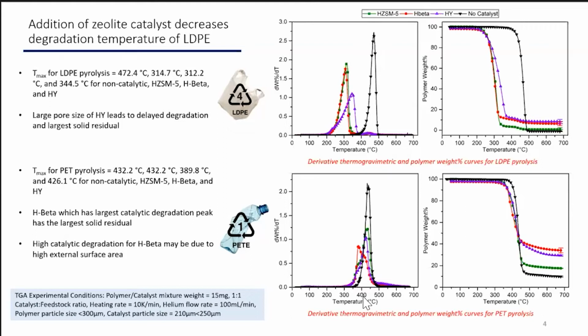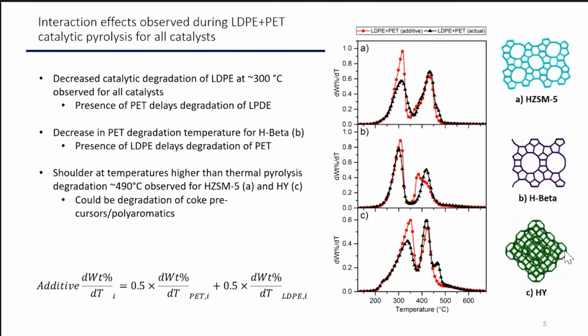And another thing that we observe with PET is that there is a very high solid residual. And this is due to PET being a charring polymer. And we also noticed that the catalyst of the H beta and the HY result in a much larger solid residual, which is made up of both the non-catalytic char and the catalytic coke. And we believe this is due to the H beta and HY having the larger pore size than this HZSM5 catalyst.